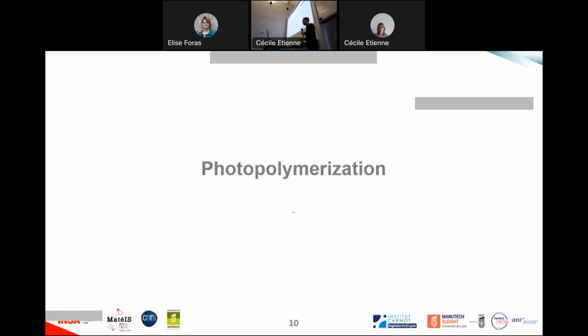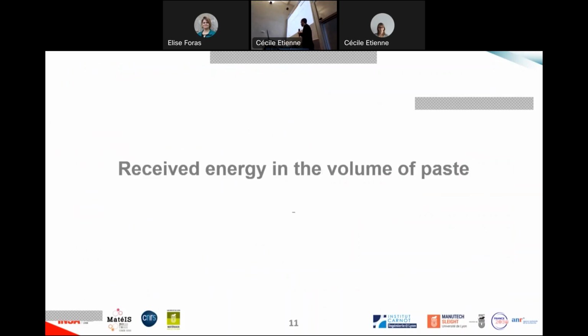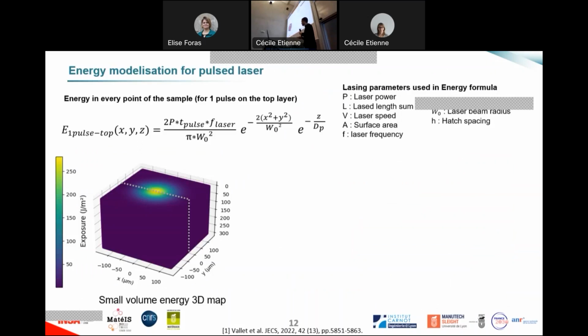Now, talking about photopolymerization, first I wanted to use a model that has been developed to calculate the received energy in the volume of the paste. It's not something that is always done when we try to characterize the photopolymerization. Here I wanted to understand how much energy has been received by each voxel in my sample. So I used this model, which calculates the energy received from one pulse, and you see the dependence on several parameters that I can change during my process. It permits me to adjust the process by making these calculations.